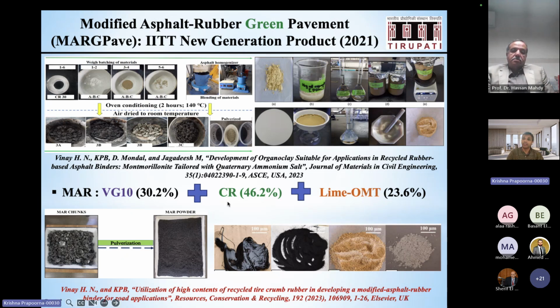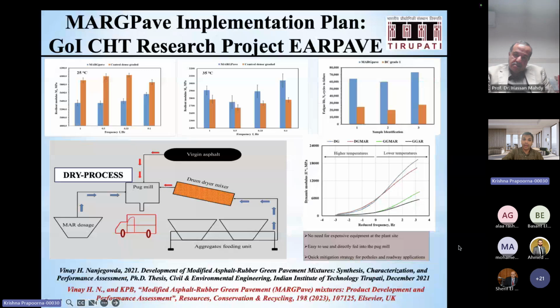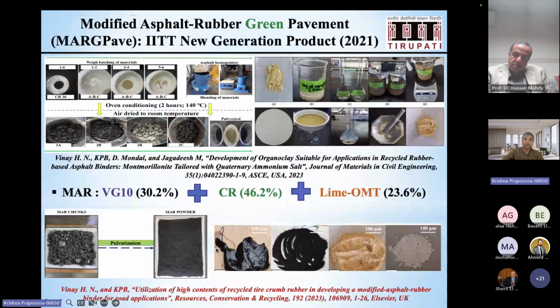That brings in that win-win situation, waste to wealth. So it's a resource that is conserved and also recyclable. So that's how this modified asphalt rubber has been prepared by us. You can see here modified asphalt rubber powder pulverized from the chunks. And now we've also gone into the other stage where we are replacing the montmorillonite with fly ash, pond ash, ground granulated blast furnace slag, and many other industrial wastes, including composite waste.